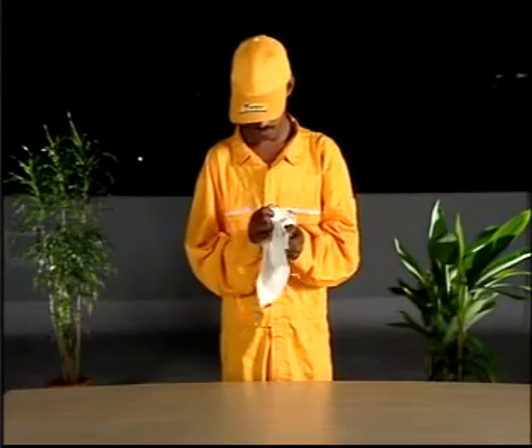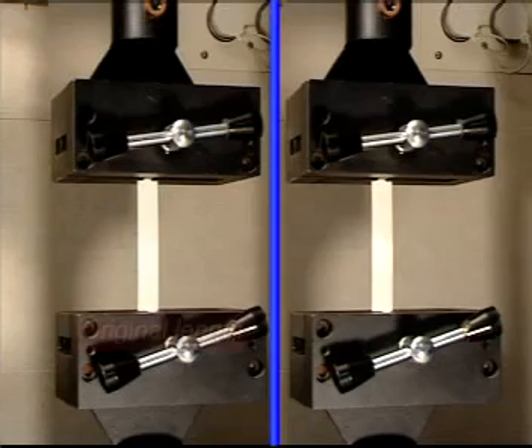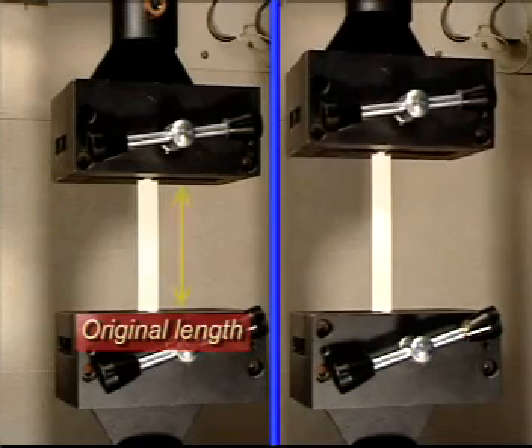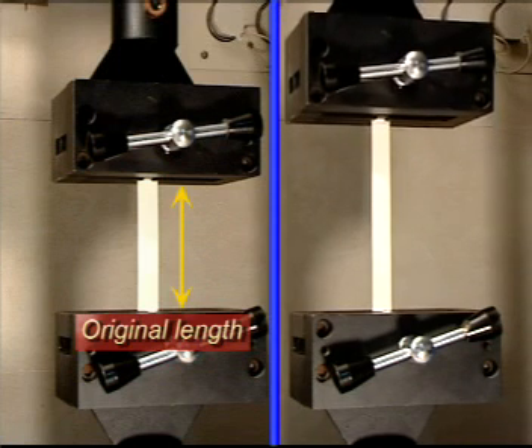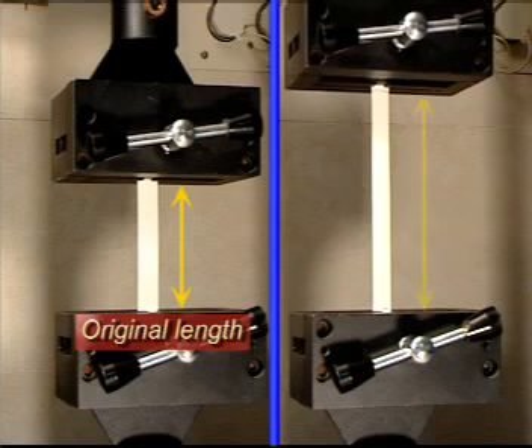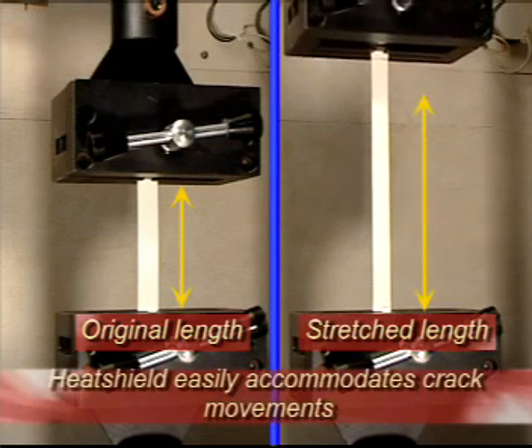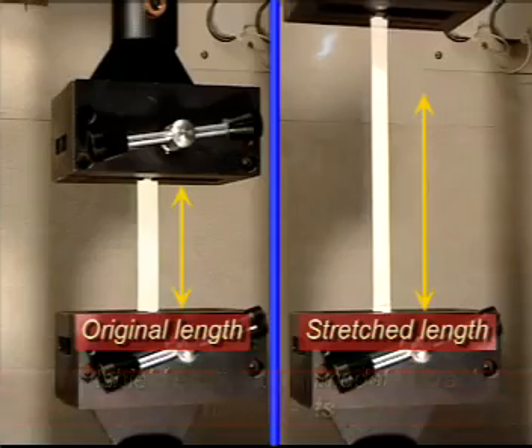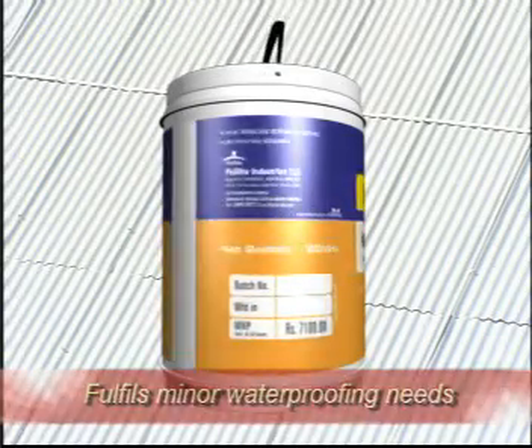Yes, it does. However, waterproofing is not a primary application of Heat Shield, and therefore it cannot replace the main waterproofing treatment. Regarding the crack bridging abilities, this is a membrane of cured Heat Shield. As you can see, Heat Shield is flexible. This film of Heat Shield is being tested for its tensile properties. As we see, Heat Shield can stretch to more than twice its length. Therefore, Heat Shield can easily accommodate the movement in hairline cracks and can fulfill minor waterproofing needs.